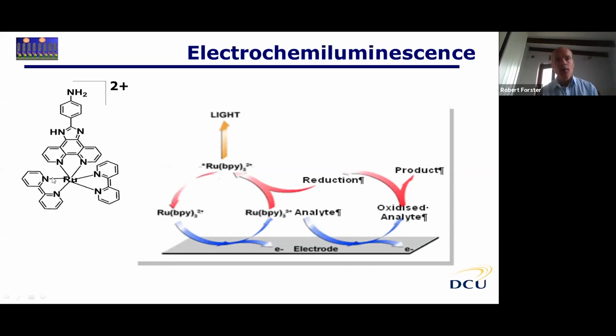This is the one we're looking at the moment. It has an amine functionality that we can bind to biological molecules, but fundamentally you oxidize the ruthenium 2+ at an electrode surface, generating ruthenium-3. You then bring in a co-reactant, which reduces the 3+ to 2+, but it's in an electronically excited state, and that relaxes by emission of light. So the key features: we apply a positive potential, oxidize the ruthenium, and the ruthenium emits light.